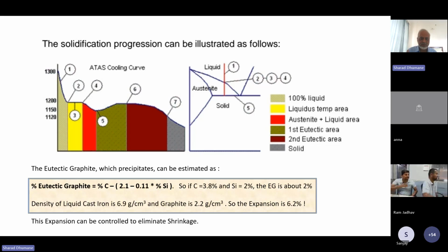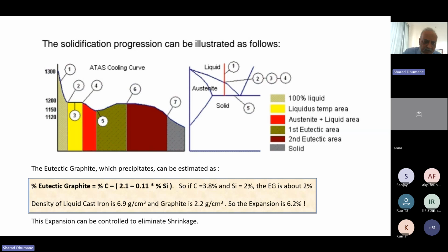Then you cool the water, and that excess salt again comes out. So similarly, salt solubility was high in hot water but low at lower temperature, so that excess salt precipitated. Similarly, the excess graphite which is dissolved in the liquid, when that liquid becomes solid, that excess graphite has to come out. And this is very interesting. That excess graphite is what is helping us to take action on the solidification shrinkage, and that is what we are going to discuss.